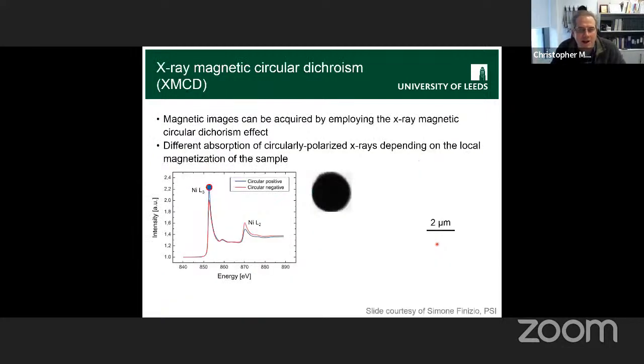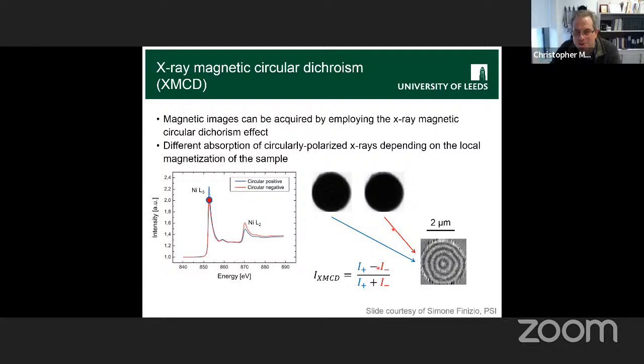So to make a magnetic image, you would go to, say, this nickel L3 edge here. This is a disk of permalloy. This is a nice example that Simone made to show us how it worked. So you take an image, and here it is. And then you flip the helicity of your light, and you take another image, and here it is. And at this point, you're thinking, well, I can't see much there. But if we take the difference over the sum of these two images, then these rings appear. And that's these ring-shaped magnetic domains inside this permalloy disk, which is mostly made of nickel.